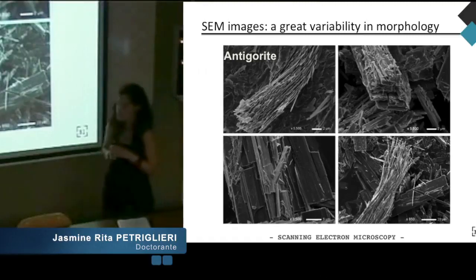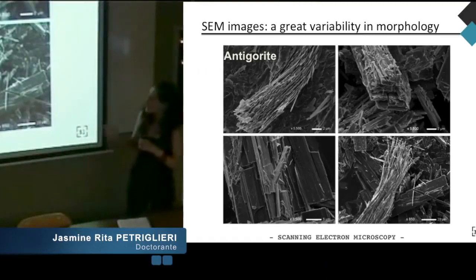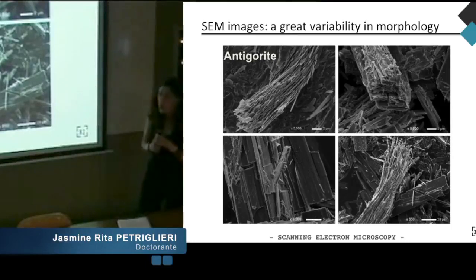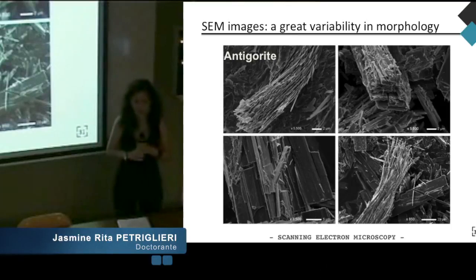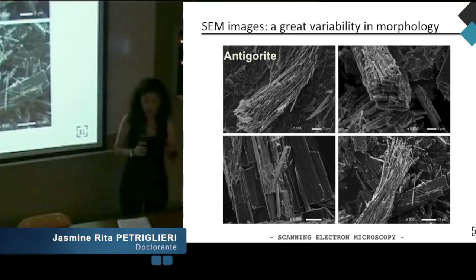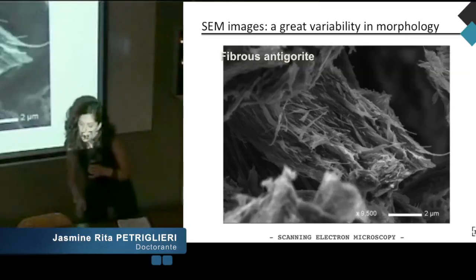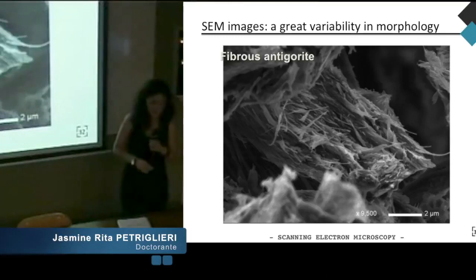a great variability is observed, from a lath-shaped morphology to a more fibrous one. Generally, the lamellae of antigorite show a general fibrolamellar aspect with, at the end, a fiber more curvilinear and flexible, and in this case, partial conversion into chrysotile is suggested.